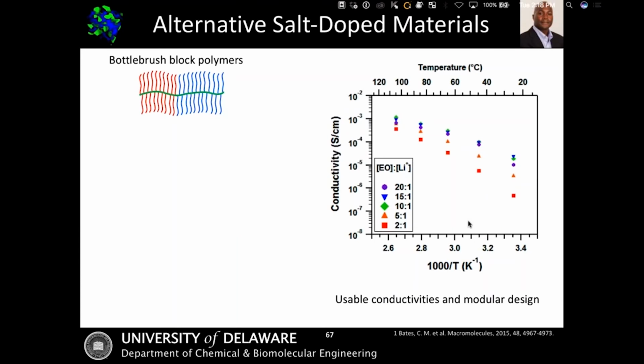salt-doped polymers? Because you can start to see that we can have some increase in conductivity, but these materials aren't necessarily ideal. If you looked at or noted the conductivities in the previous slide, we were at on the order of about 10 to the -5 Siemens per centimeter, and we'd like to be able to get higher, also improve the mechanical stability and the processability of these materials even further.